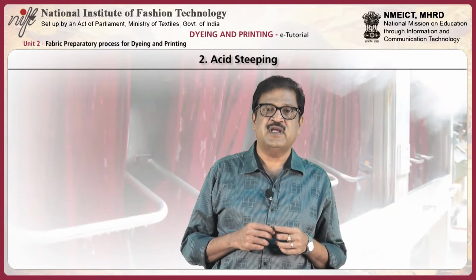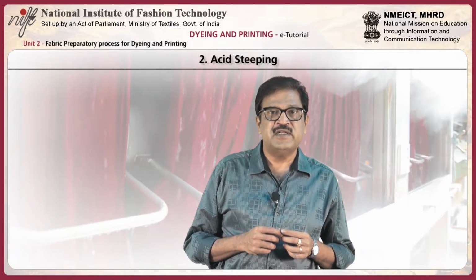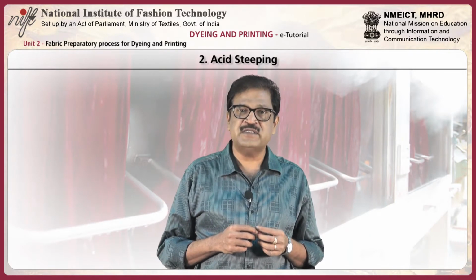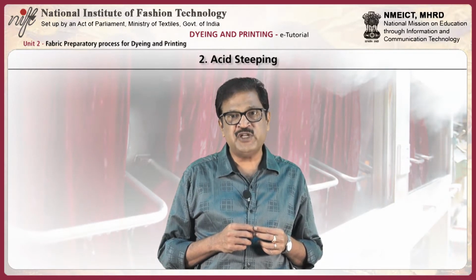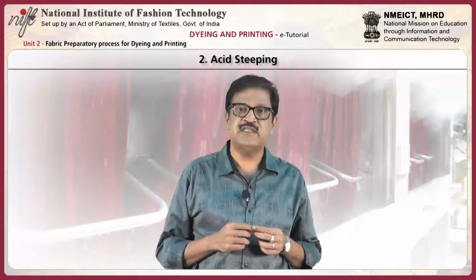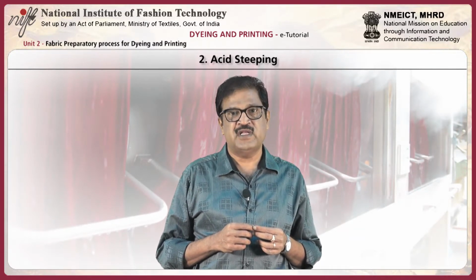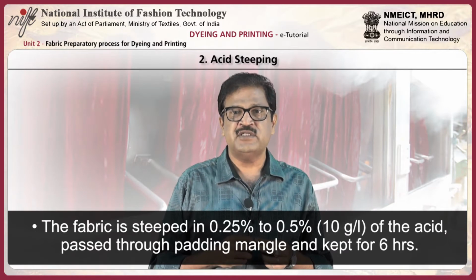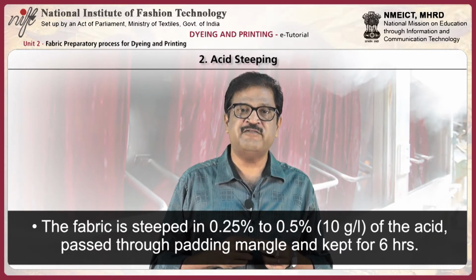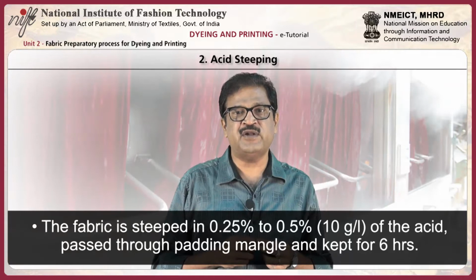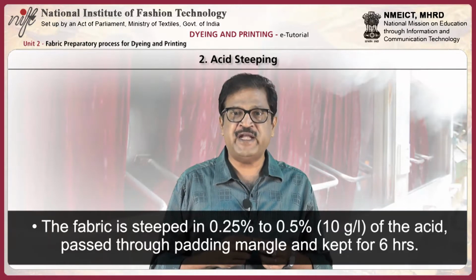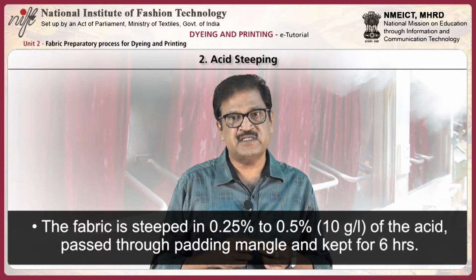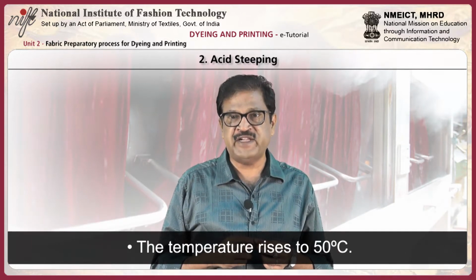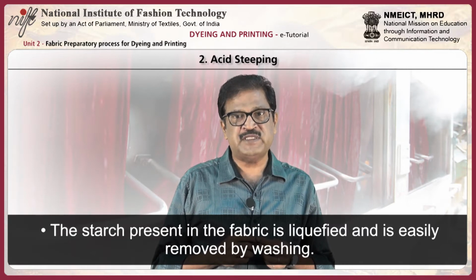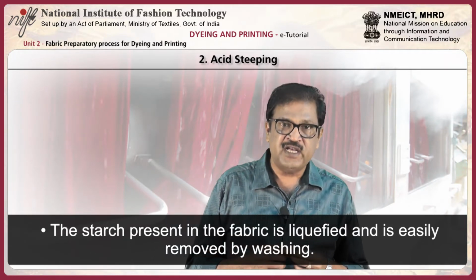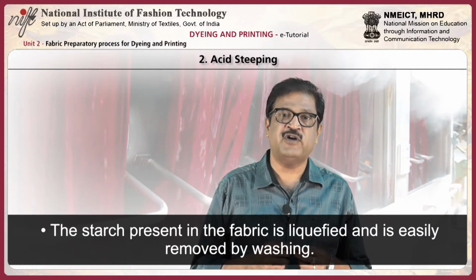Acid steeping. In the acid steeping method, dilute hydrochloric acid or sulfuric acid or a mixture of both are used to hydrolyze the starch from the sized fabric. The fabric is steeped in 0.25 to 0.5 percent or 10 grams per liter of the acid, passed through a padding mangle and kept for 6 hours. The temperature rises to 50 degrees Celsius. The starch present in the fabric is liquefied and is easily removed by washing.